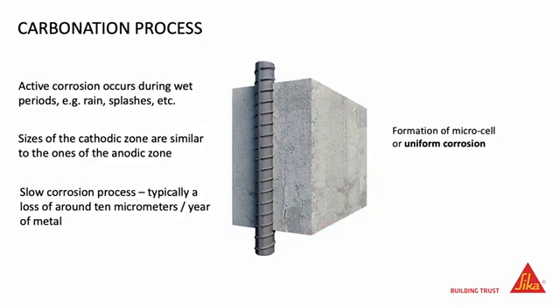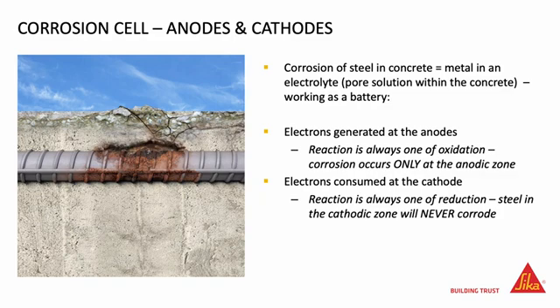When this carbonated concrete becomes wet during rain, the concrete conductivity is increased through low electrical resistivity of the water in the pores. A multitude of microcell corrosion forms rust uniformly on the depassivated rebar. The produced rust has a larger volume, creating heavy stress on the concrete cover, leading to cracking and delamination.